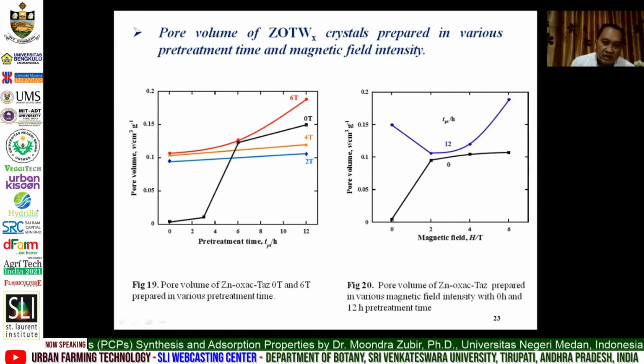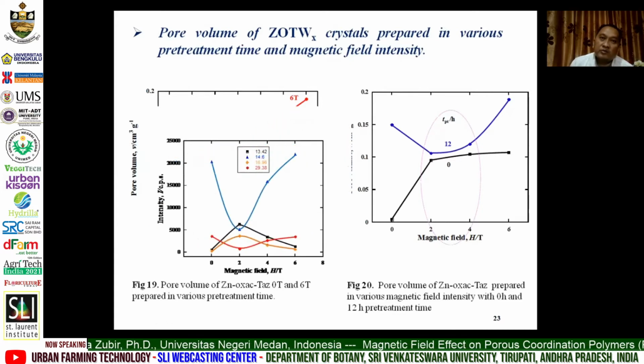And you can see the 0 Tesla crystal has the pore volume after 3 hours, but the magnetic field crystals, all 2 Tesla, 4 Tesla, and 6 Tesla, already form the porosity without the pretreatment time need. And if you compare the magnetic fields, 2 Tesla and 4 Tesla also have a specific pore volume if compared with 0 Tesla and 6 Tesla. So it's considered to be supported by the XRD pattern intensity change before for 2 Tesla and 4 Tesla crystal.